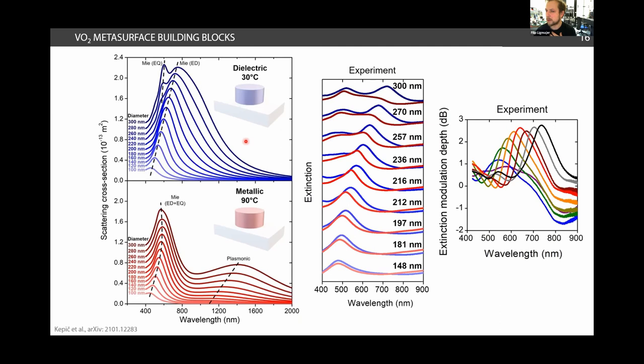Okay thank you very much and I have a second question is that if you use the VO2 as a spacer so what is the thinnest film you can actually, so if the film is very thin can you observe some change about transition temperature or some? Yeah yeah it's that's one of the things we are thinking of and we have some future work ready but it is a problem if you want to make VO2 very thin, you have trouble to get high quality switching and nice films. So there are a couple of works describing depositions of ultra thin VO2 films. If you drop me an email or I can refer to you to these words. It's not an easy task. Some people claim they have nice VO2 films but they don't show in my opinion sufficient evidence for that.